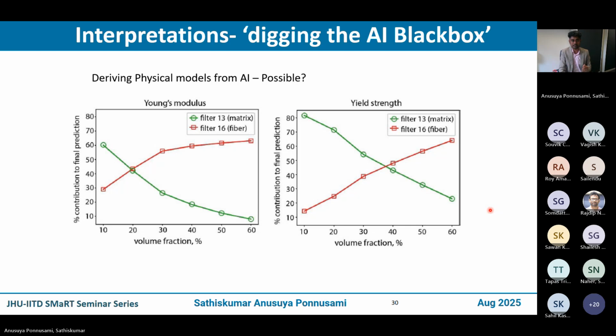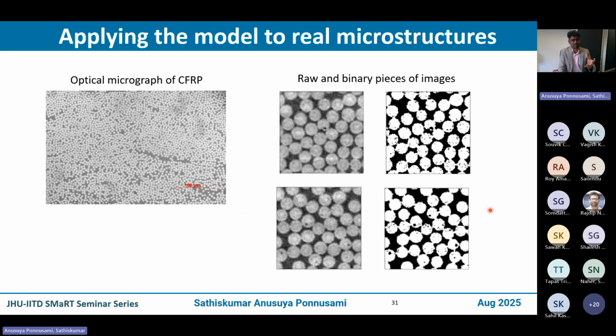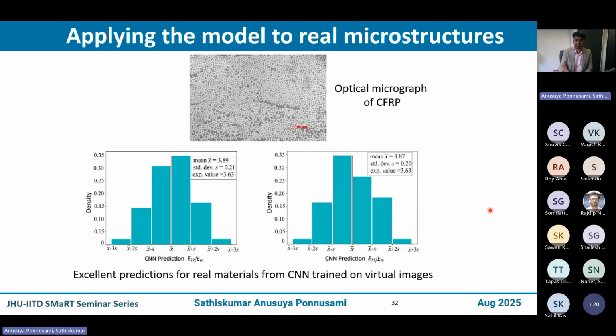Okay. Great. We also did a little work on taking a realistic experimental microstructure. This is an optical micrograph of a carbon fiber reinforced composite. So what you do is clean up and take different cropped images of those so that you can feed them in. The only pre-processing step is converting them to binary images, and you can see the quality of the image is quite poor, but we feed it into the model and see how it predicts. And what we observed is it predicts reasonably well. If you look at the non-dimensionalized Young's modulus, the experimental value is 3.63, whereas the prediction by the CNN is about 3.88, which for the poor quality of the image that you fed in, is quite reasonable in my opinion.